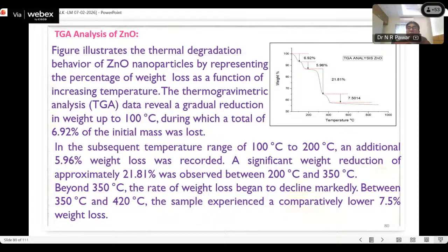Now, this analysis plays a very important role, especially for the stability and to know the contents of that material. The figure illustrates the thermal degradation behavior of ZnO nanoparticles by representing the percentage of weight loss as a function of increasing temperature. The TGA data reveal a gradual reduction in weight up to 100 degrees Celsius, during which a total of 6.92% of the initial mass is lost, as shown here.